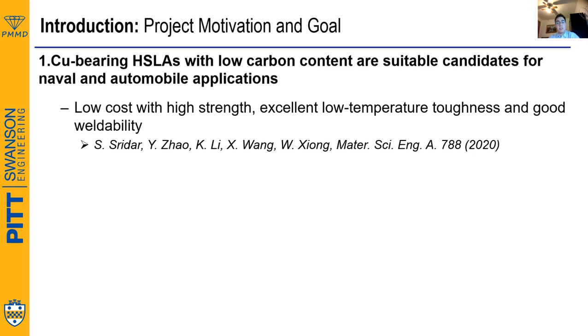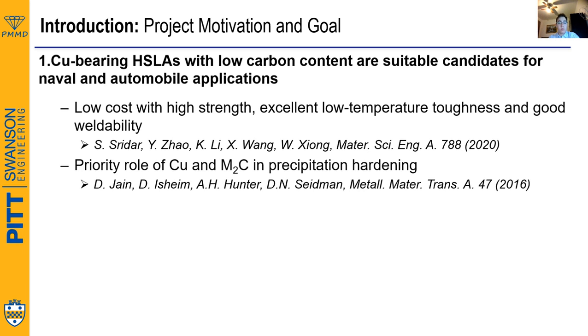Finally, the expected decrease on strength associated with the lesser amount of carbon is offset by the precipitation strengthening effect of copper. Perhaps the most remarkable characteristic of these steels is this last one. The combined strengthening effect of copper and M2C carbides in fairly low amounts, less than 3%.